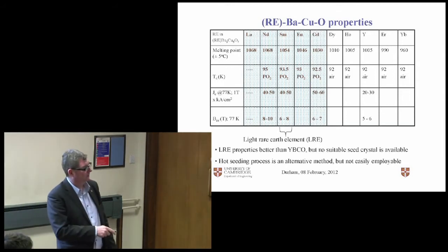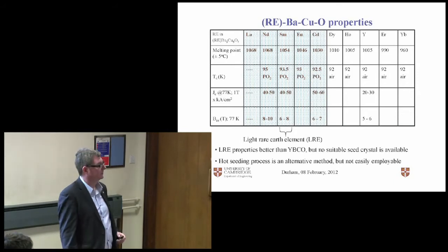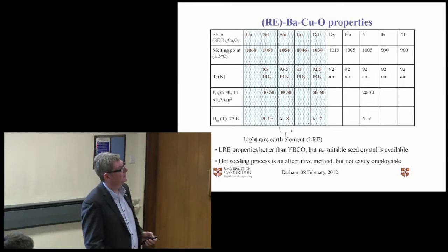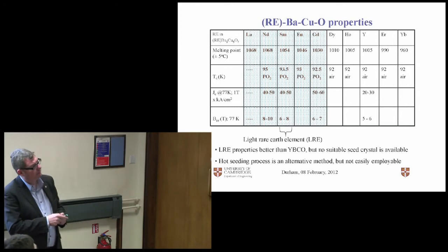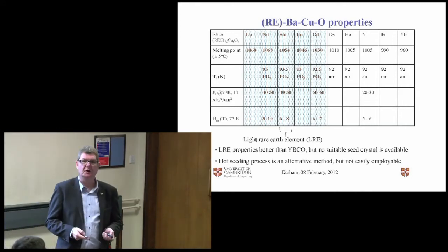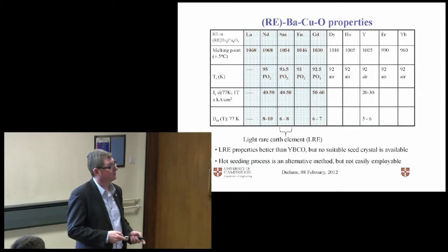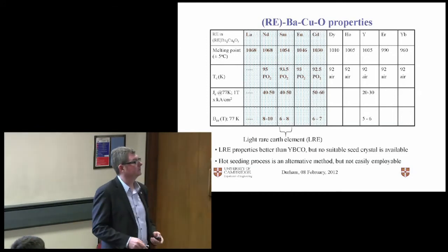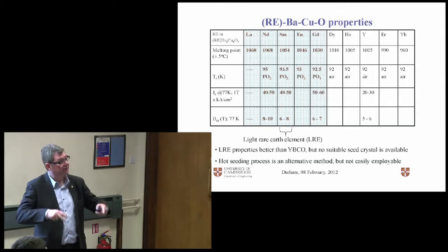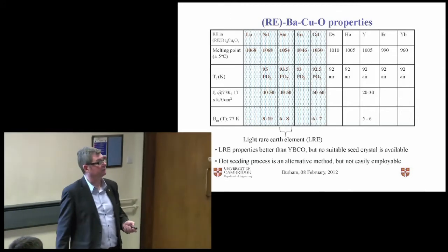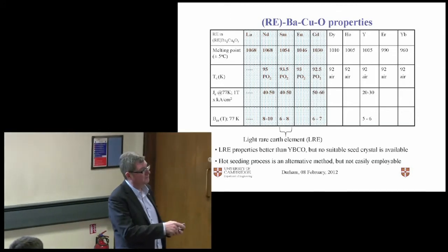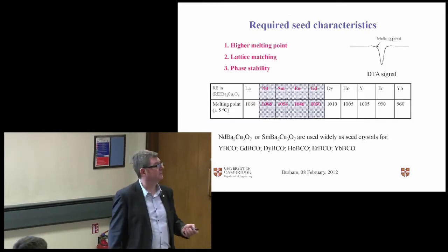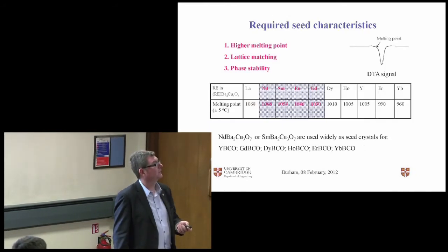One way you could do it is a hot seeding process, and the Japanese are very good at hot seeding. One problem with these light rare earth barium copper oxides is that you have to process in a reduced oxygen atmosphere, because if you don't, you get substitution of the rare earth element on the barium side, and TC comes down and the properties become inferior. So you've got processing challenges, and you've got a seeding challenge.